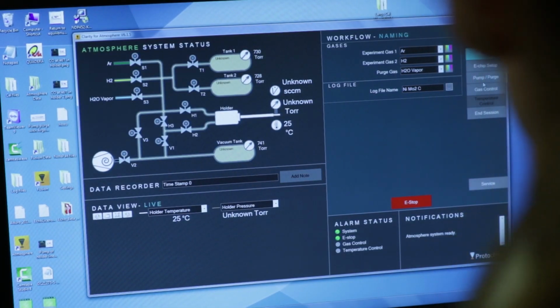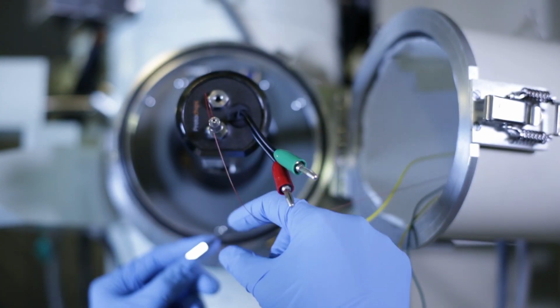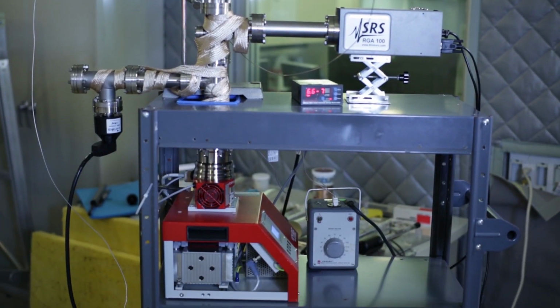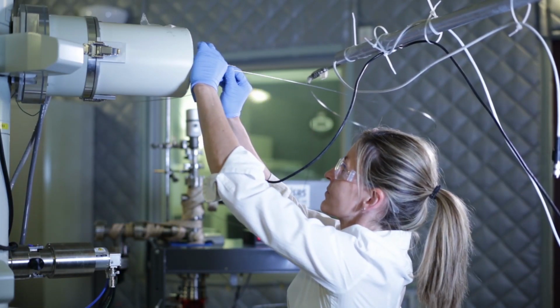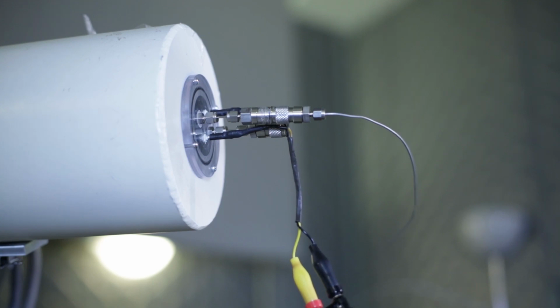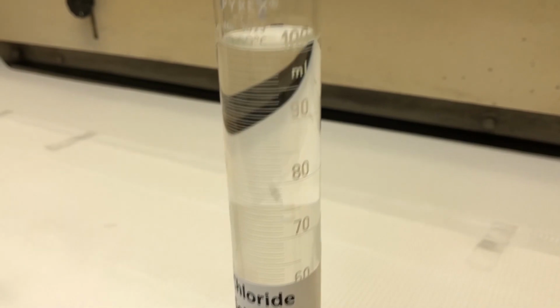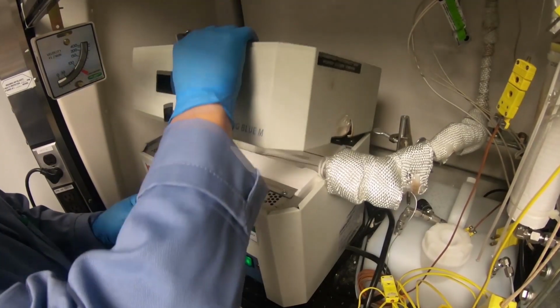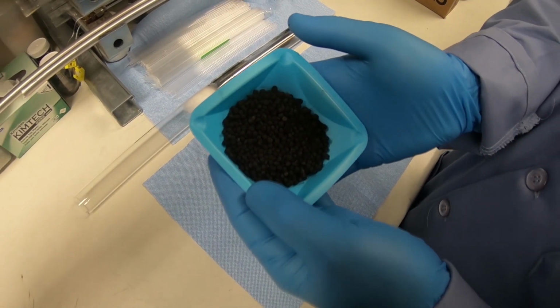atmospheric pressures. In-situ STEM at NREL uses a prototype system that includes computer control, gas delivery manifold, and in-situ gas reaction TEM atmosphere holder. Recently, we performed additional upgrades to the in-situ system, and we added a residual gas analyzer that is connected to the stainless steel capillary at the end of the atmosphere TEM holder. This allows us measurements of the gas on the exit side and quantitative measurements. Recently, it's been used for studying NREL-developed molybdenum carbides, where we try to regenerate the spent catalyst that was tested in a bio-oil upgrading reactor at PNNL.